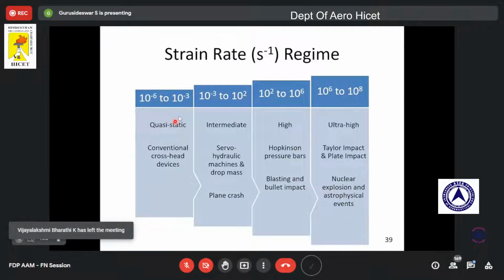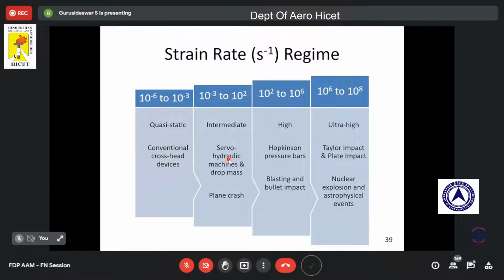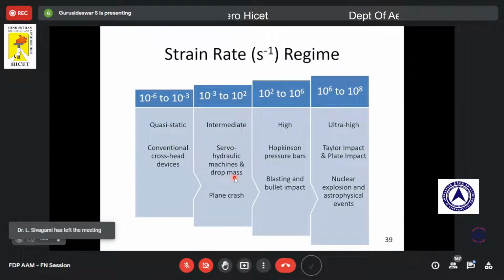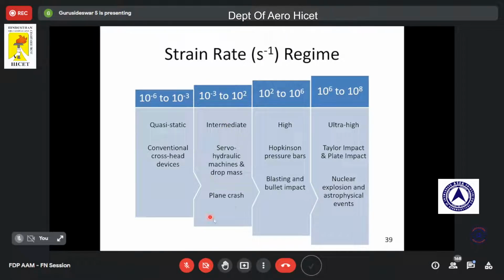Here again, I wanted to explain the different strain rate regimes. 10⁻³ is the region where we can say it's static loading, and 10⁻³ to 10² per second we say is the intermediate strain region. We can use a servo-hydraulic machine or drop mass. Generally plane crashes and vehicle crashes are subject to this kind of loading, so it is important to understand the properties of material at this regime. And for high strain rate, we go for the split Hopkinson pressure bar. Again, this is the range, 10² to 10⁶, and the application is blasting and bullet impact.